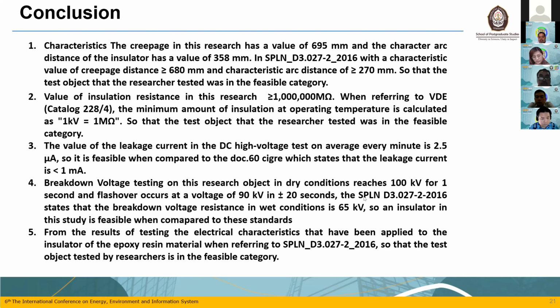According to SPLN, breakdown voltage resistance in wet condition is 65 kilovolt. So the insulator in this study is feasible when compared to the standard. From the result of testing, the electrical characteristics that have been applied to the insulator of the epoxy resin material, referring to SPLN D3027 to 2016, show that the test object of this research is in the feasible category.